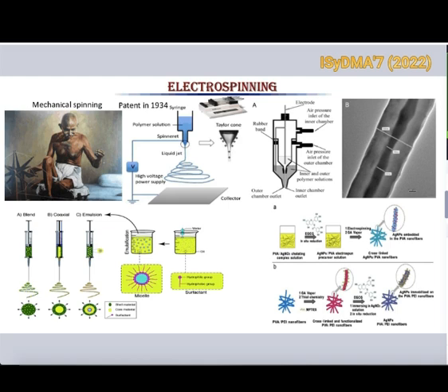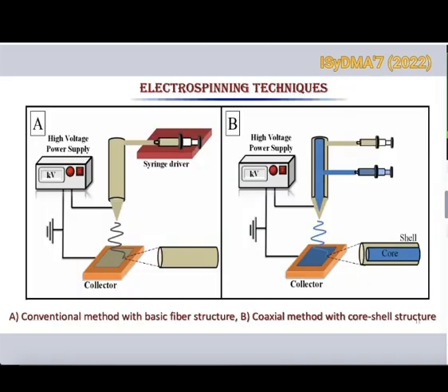The method involves essentially, as you know, an electrohydrodynamic process in which a polymeric drop is electrified and forms a Taylor cone and then proceeds towards the substrate where we can collect it by using different methods. This slide simply shows different configurations which we have made, and I'll show you in the following slide a couple of configurations which are very commonly used. So these are two out of several configurations which we have used.